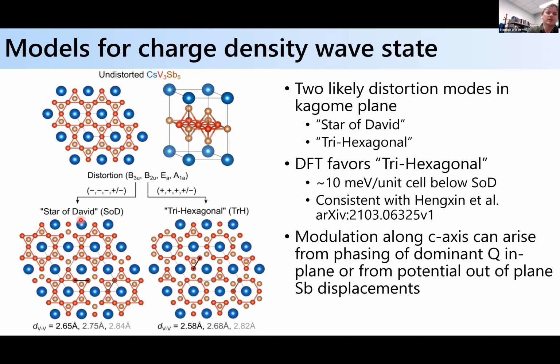And so this Star of David structure is shown here. But if you run these 3Q vectors in plane in the reverse, if you turn to plus, plus, plus, then you get this other structure, which we call the trihexagonal structure. Some people call it the inverse Star of David structure. And then the fourth mode basically controls the effective displacement of the antimony atoms out of the plane. So this particular mode could give you some interplanar modulation between the orders.